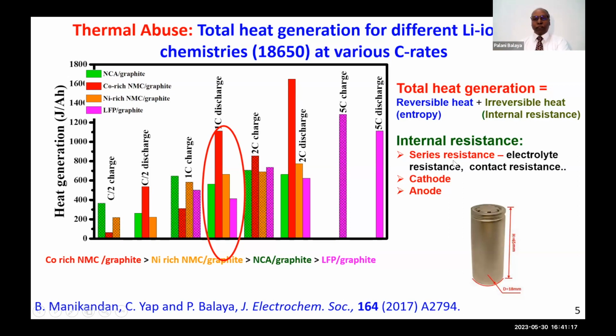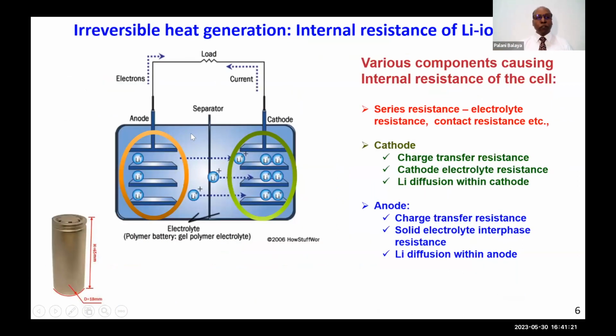Now let's look at the internal resistances. So you can see here, this is the positive electrode, this is the negative electrode, and this is the separator. Because this is in the discharge state, I refer to this as the cathode and anode. Now, when you do this, what happens? You could have internal resistance because of the electrolyte and the contact. So you have the contact here, you can see. Or you can have something due to the cathode, what is happening in the cathode. It could be the charge transfer. We are transferring the electron and the lithium ion; putting together lithium ion and the electron, I call charge transfer. That could give rise to internal resistance. Or this positive electrode in contact with the electrolyte, we call it cathode electrolyte resistance, or the lithium ion and the electron, we call it chemical lithium diffusion within the positive electrode. That's the last one. These three can give rise to so-called internal resistance.